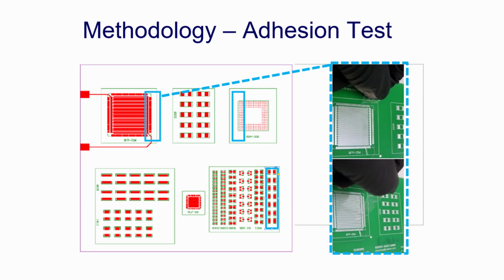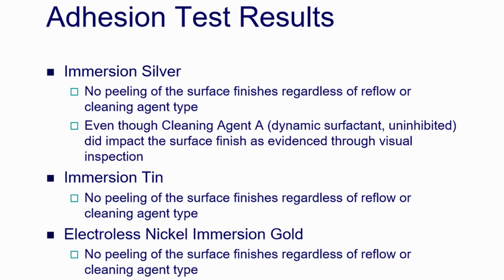The next analytical test that was conducted was the adhesion test. This test made use of a 3M 600 tape that was applied on various areas of the board, and it was forcibly removed, and the tape was then inspected under a microscope to check for any particles of the plating that got removed during the removal process. It was found that all the cleaning agents and all the surface platings were completely fine, and there was no plating removal upon the application of this adhesion test.